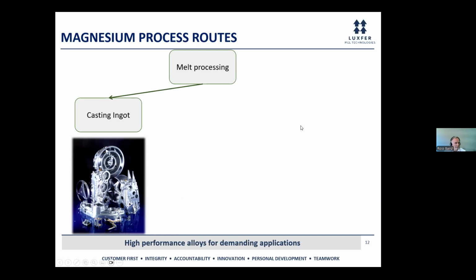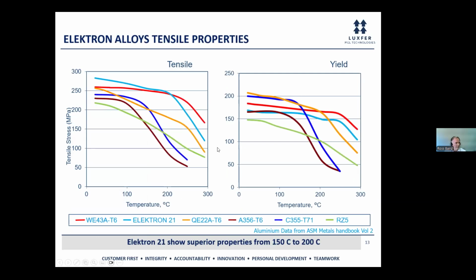So if we consider the sand casting process, the traditional aerospace alloys include alloys such as RZ5 or ZE41, WE43, and QE22. And the standard aluminium alloys are A356 and C355. We now have an alloy called Electron 21, which is addressing high temperature performance. What you'll see from these graphs is that the A356 and C355, whilst they are comparable at room temperatures, once we start to get up into the range of 150 to 200 degrees Celsius, the properties drop off.